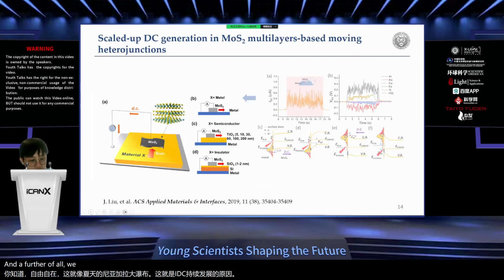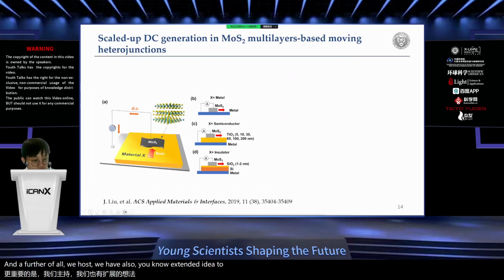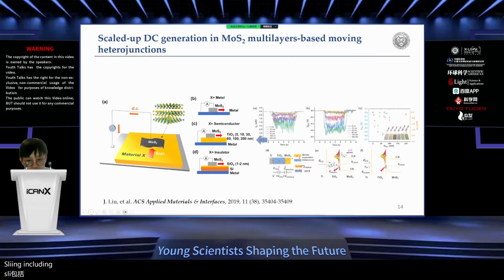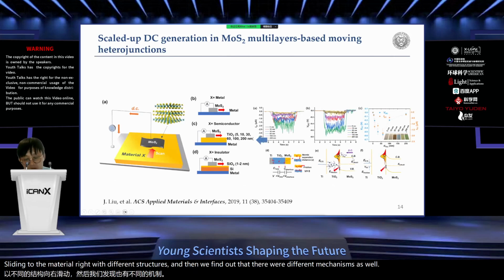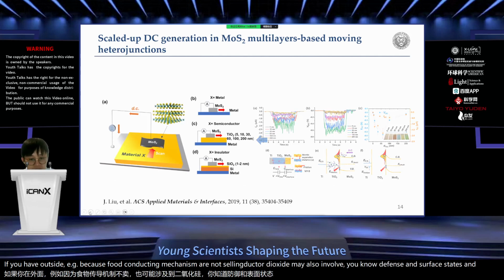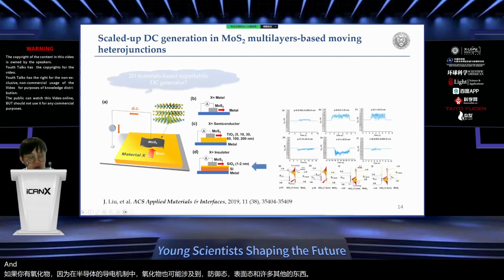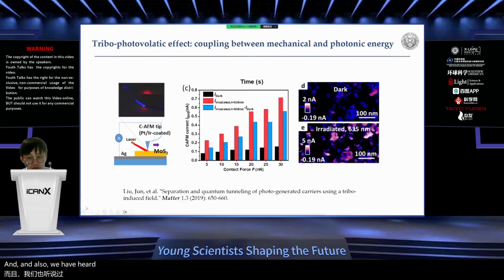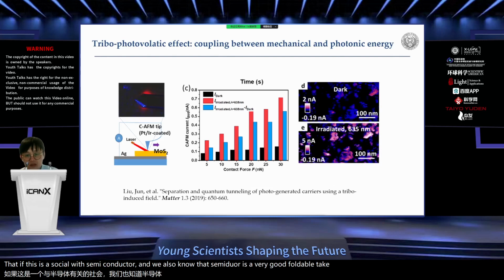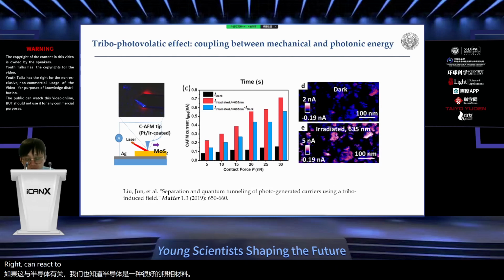And then further on, we have also extended the idea to, for example, the macroscopic sliding 2D material, right, with different structures, and then we find out that there were different mechanisms as well. If you have an oxide, for example, the conducting mechanism of the semiconductor oxide may also involve defects and surface states and many other things. Also, we were thinking that if this is associated with a semiconductor, and we also know that a semiconductor is a very good photovoltaic material, right? It can react to irradiation. So can we actually combine these two effects? So the answer is yes.